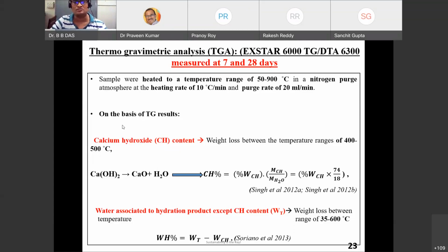Now, on the basis of thermogravimetric results, consider the calcium hydroxide. The weight loss for calcium hydroxide occurs at 400 to 500 degrees centigrade. So remember, the decomposition of calcium hydroxide happens within 400 to 500 degrees centigrade. This equation is already given by Singh et al., where they show how you can determine the calcium hydroxide content from TG results: Ca(OH)2 → CaO + H2O, and the CH percentage is determined from the weight loss divided by the mass of H2O. So the percentage of calcium hydroxide you can determine through this equation.